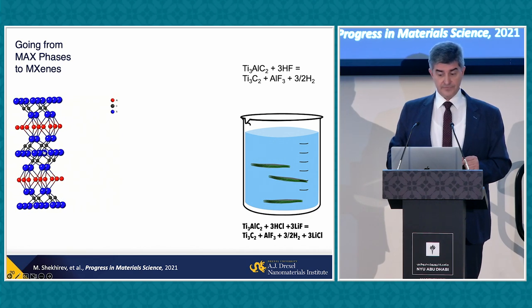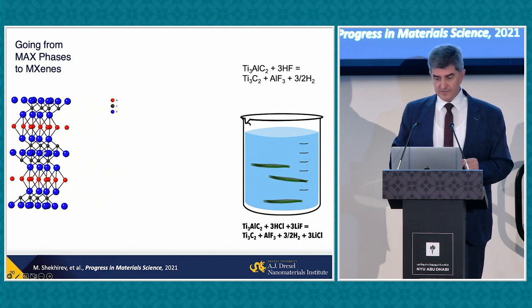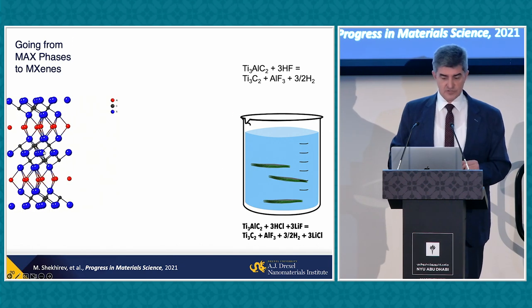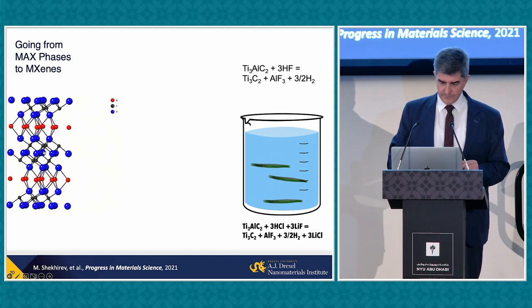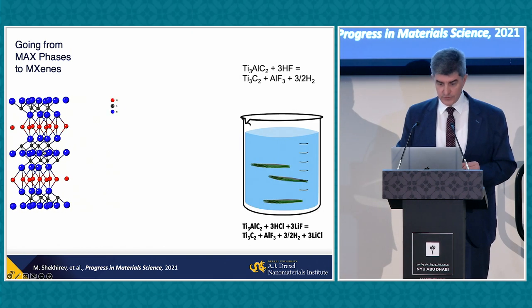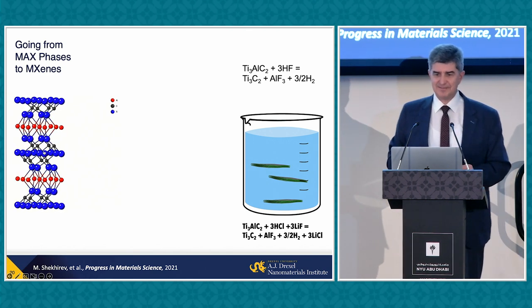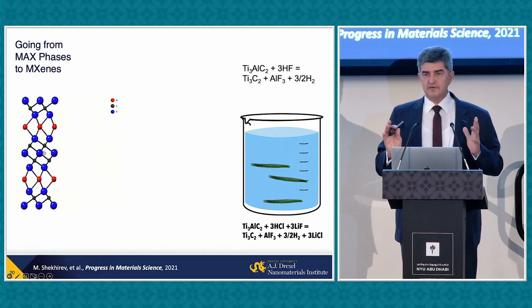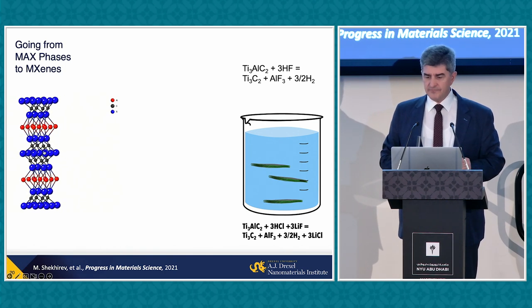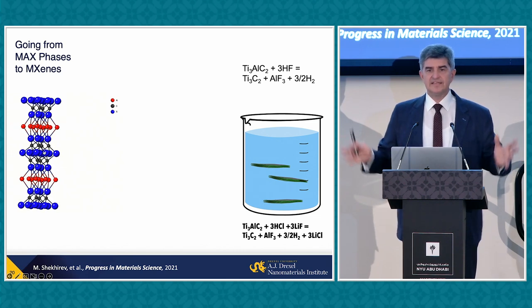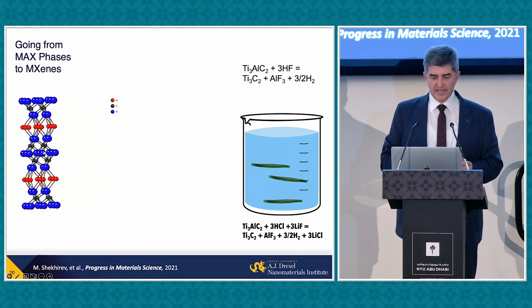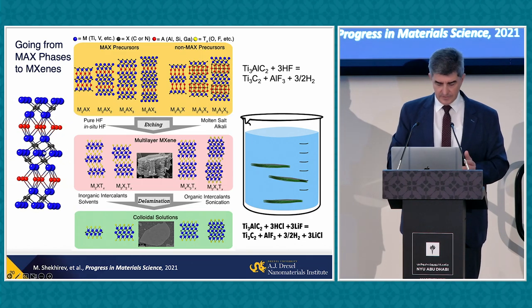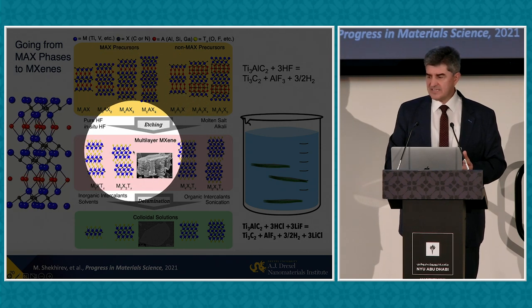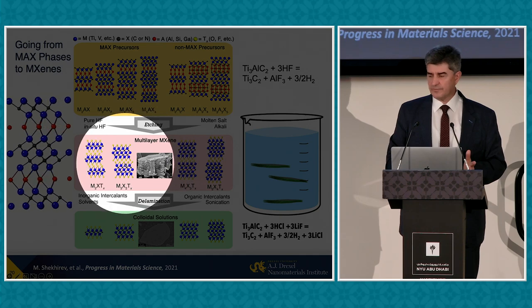However, what happened? We did it. And we did it by etching MAX phases. And I'm not sure why my video is not working. Well, it used to work, the animation here, believe me, when we tested it before the talk. But basically what we did, we put this material into acid and etched aluminum or silicon layers away, making these two-dimensional layers out of etched material. So pretty much breaking strong bonds in MAX phase, separating them, making them look something like exfoliated graphite or vermiculite clay, layers weakly bonded, and then separating single layers here.